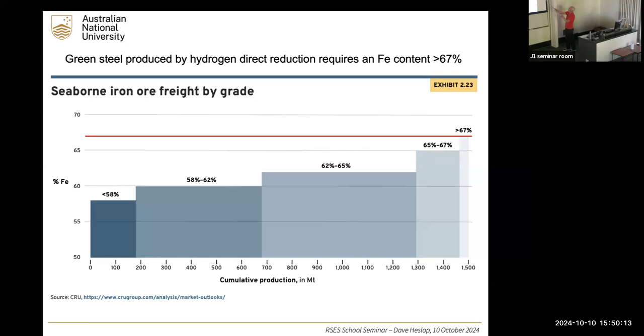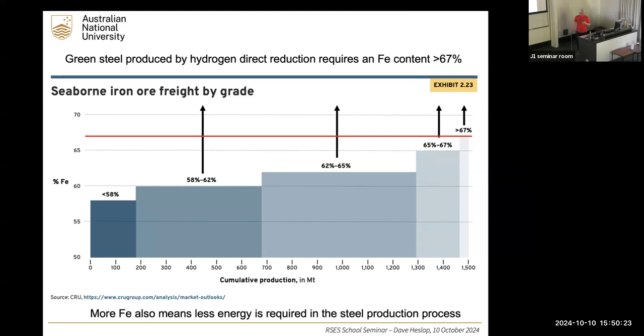So getting back to the green steel and this desire to increase the amount of iron, remember for green steel production, we need iron above 67%, this red line here. Now that may come over as a slight magic number, but the story gets a little bit more complicated than that, because what you want to do for all of these ores is increase the iron as much as you can. More iron means less energy is required in the steel production process. So even if you're producing your energy from renewables, you still want to use as little energy as you can. So it isn't simply a case of getting up to 67% and stopping. With this beneficiation process, there's always room for improvement until you hit 100%, which of course is never actually going to happen. So this is going to be a continuing effort to try and increase the grade of these ores.